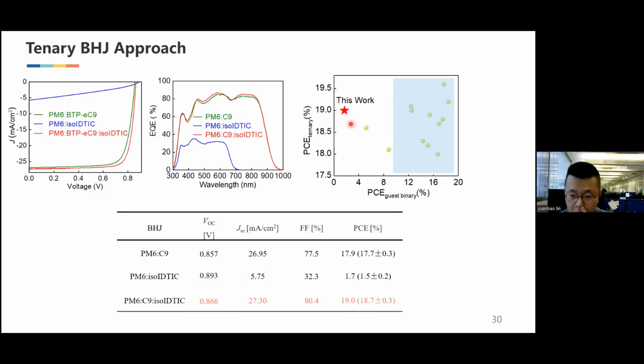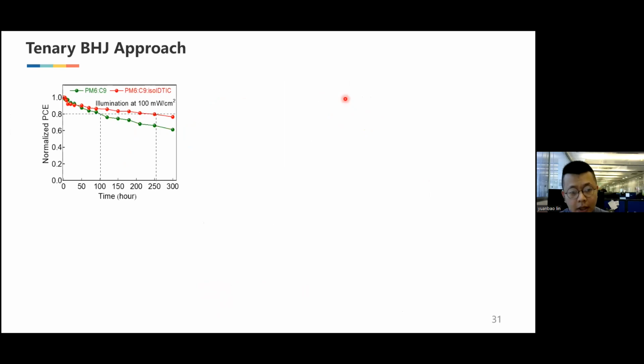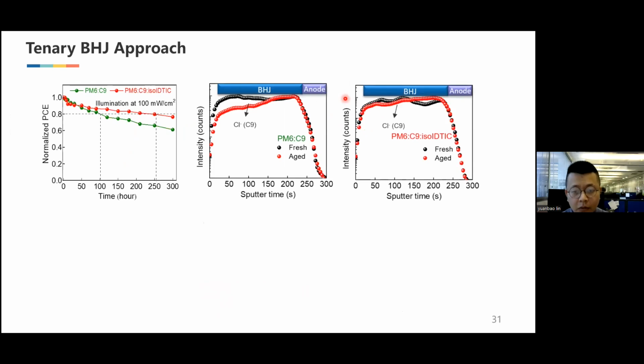We also noticed that most people, when they choose the third component for a ternary system, always choose a high-performance material. But here we demonstrate that even with a low-performance third material, we can get high performance in the ternary. We also tested the stability of these two, and the ternary has slightly enhanced stability compared to the binary.